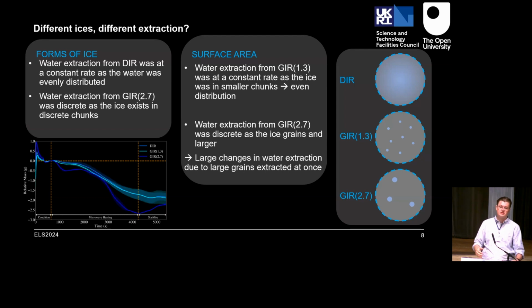As I mentioned, the smaller grains probably are acting like diffuse ice because they're diffused through the system. For the larger ice, you're seeing something quite different in the way the extraction drops. And that's probably just due to the fact that we were keeping the amount of water consistent. So you've got less of them, but larger chunks, and so it comes out in discrete forms as they heat up.